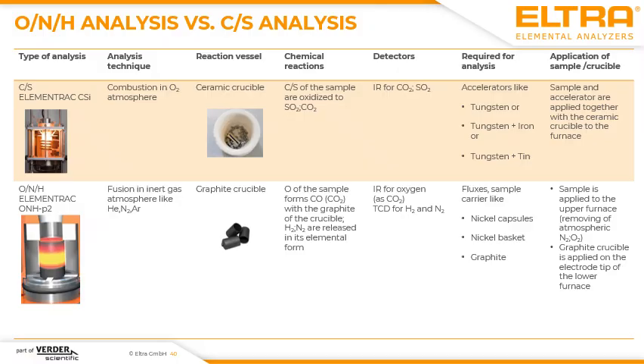You are using inert gas fusion for this kind of sample, and oxygen is measured as CO2, whereas hydrogen and nitrogen are measured in elemental form. Here you don't need an accelerator, but some samples, for example titanium, need flux material like nickel baskets or nickel capsules, and sometimes high oxygen samples need additional graphite. So here you have to take care of other accelerators and other fluxes.